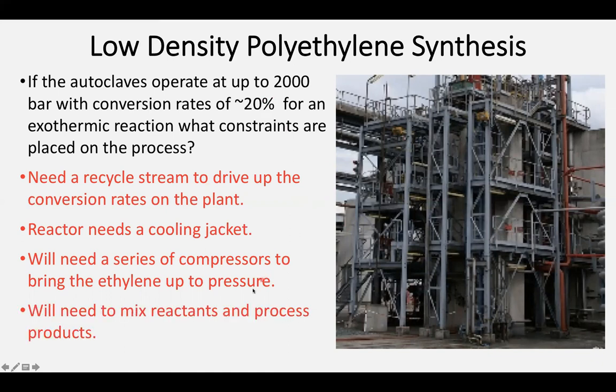Because it's an exothermic reaction and can undergo decomposition, I'm going to need a cooling jacket to counter the exothermicity. Additionally, 2000 bar is really high, so a single compressor alone isn't going to be sufficient — we'll have to use several compressors to bring our ethylene up from essentially room pressure up to this 2 kilobar. We're also going to need good mixing of our reactants and products, so we'll probably need some form of stirring, plus the ability to process and purify our products.